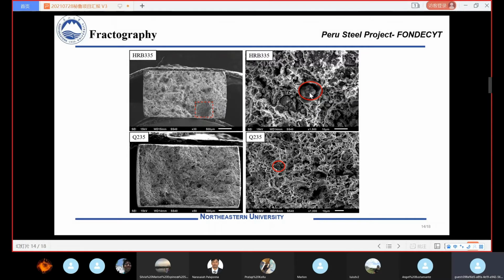It is considered that there is stress concentration during the deformation. The stress concentration occurs near these large particles, and the crack initiates inside the brittle second phase, and then crosses the whole specimen. In Q235, the size of the second phase is very small, so the number of dimples in Q235 is more than that in HRB 335.